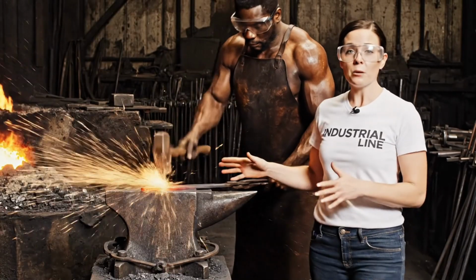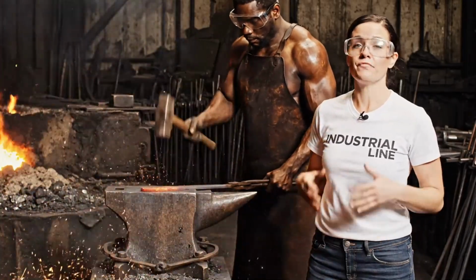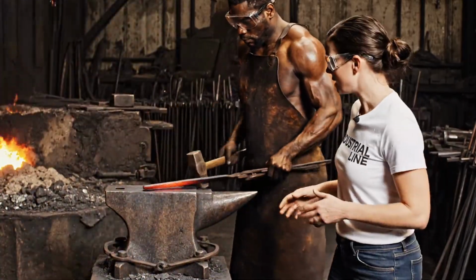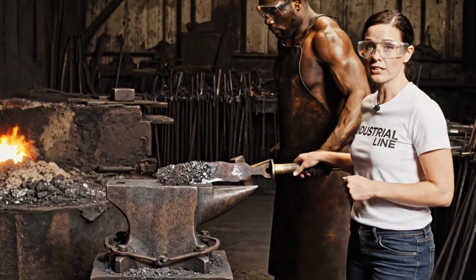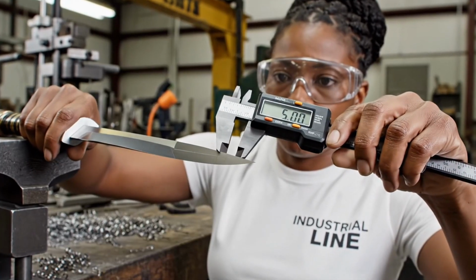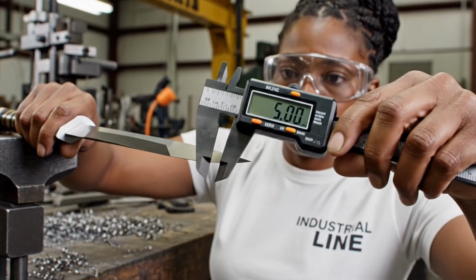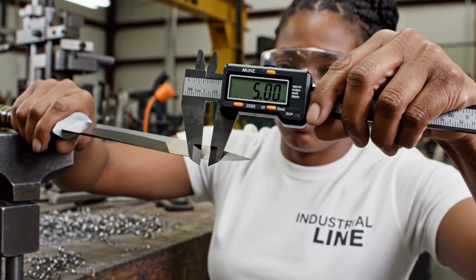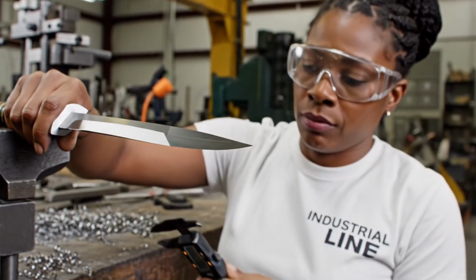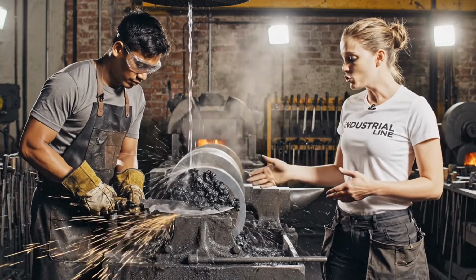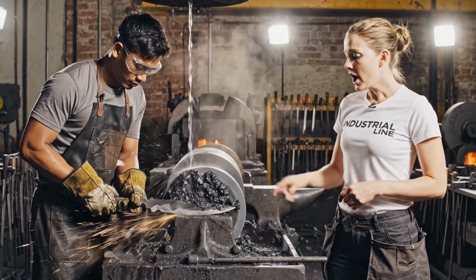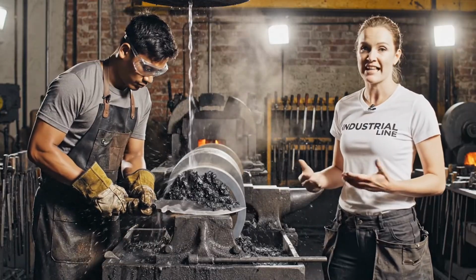The blade will be heated and shaped approximately 50 times during this phase, and each heating allows only 30 seconds of work. We thin the ha to 5 millimeters, while the mune remains thick at 8 millimeters. This differential thickness contributes to the blade's performance. This rough grinding removes about 2 millimeters of surface material, and all the folding layers are still intact deeper in the steel.